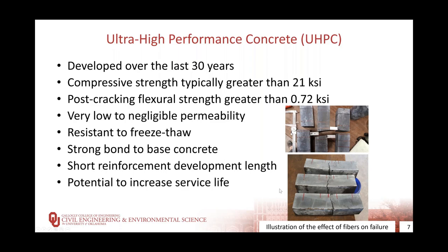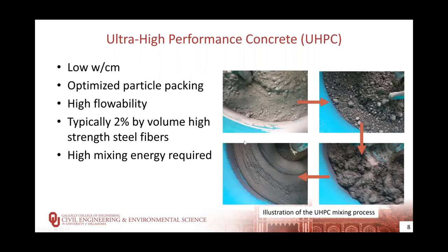Continuing with some general information on UHPC. It has a very low water cement ratio, and an optimization of the particles within the mixture to get a high flowability. Again, we have steel fibers, and those are typically included at about 2% by volume. Clay will talk about what happens if we have other percentages. And then we need a high mixing energy because there's no coarse aggregate. You can see that illustrated here on the right side in a high shear concrete mixer where we have a powder to start with. As we mix that powder, it starts to ball up and eventually creates a material with a pancake batter consistency, at which point we would add the steel fibers.